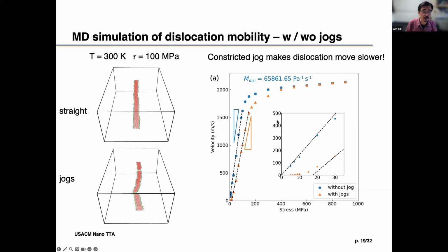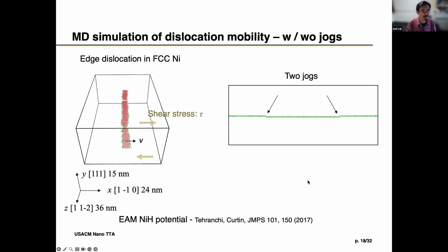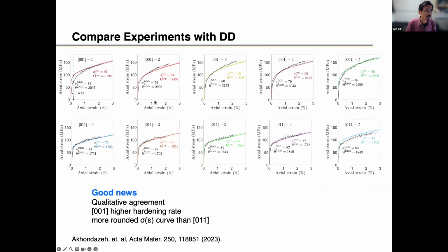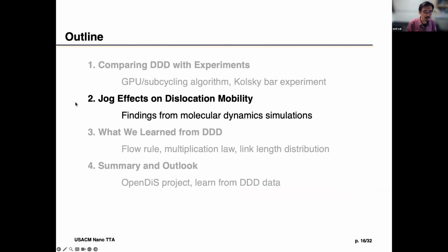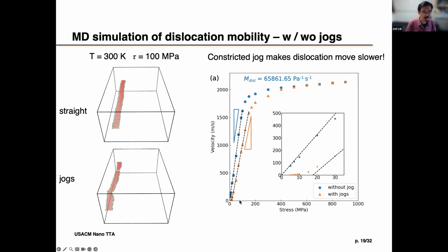And then if you repeat the simulation, in this case at 300K, at different stresses, you can see the mobility here, velocity as a function of stress. On this plot, it may not look like a lot because eventually the velocity goes very high. At very high stress, the velocities are the same. But we have to remind ourselves that in this strain hardening deformation situation, we're at very small stress here. You look at the stress-strain curve we're talking about. So we're on the order of 100, or in experiments even less stress. Down here, you can see an enormous difference in the mobility or the velocity between a dislocation without jogs and a dislocation with jogs.